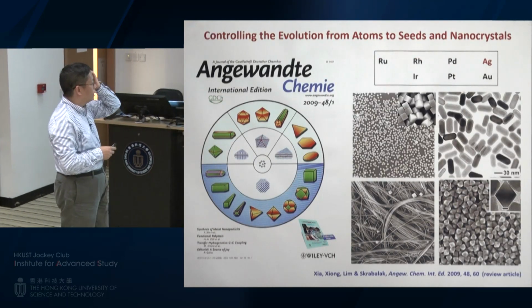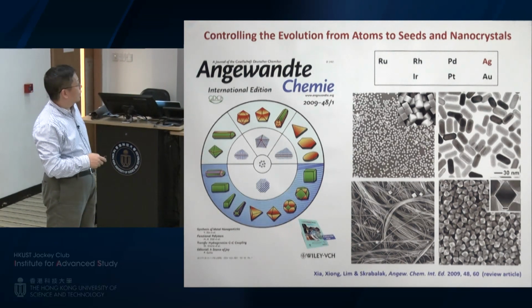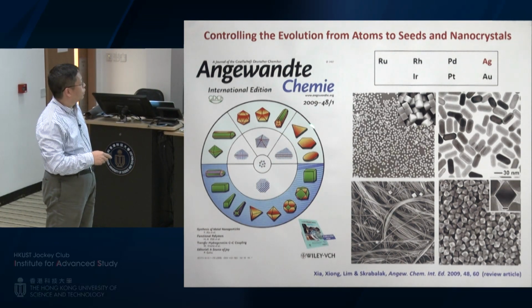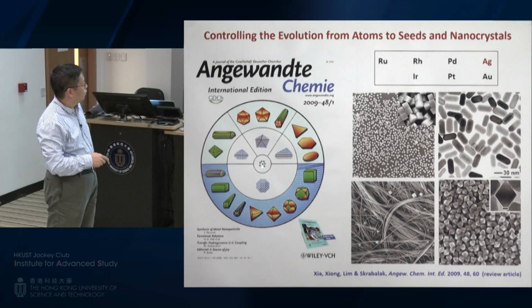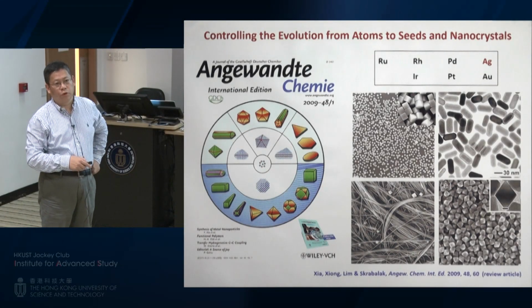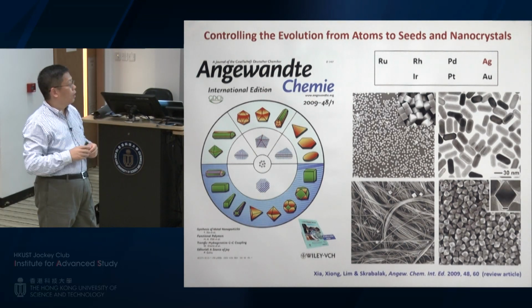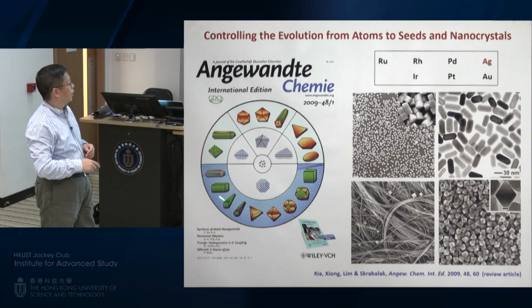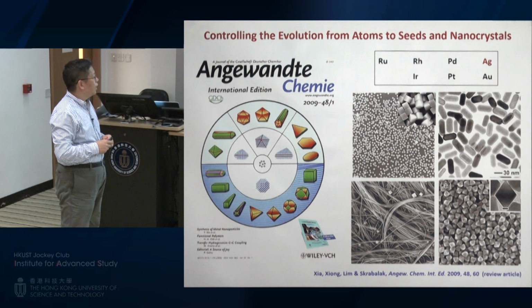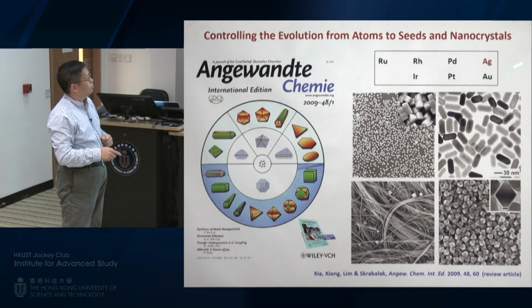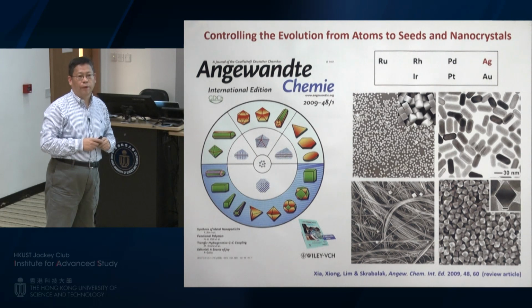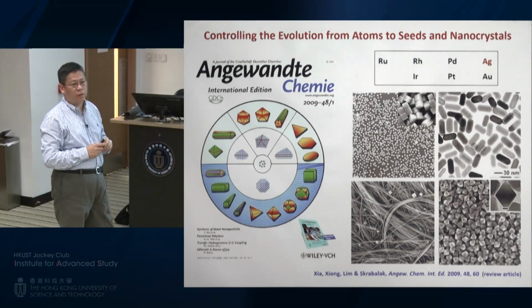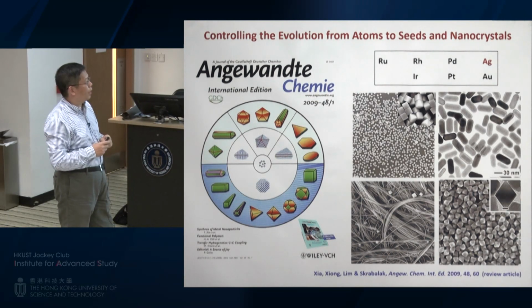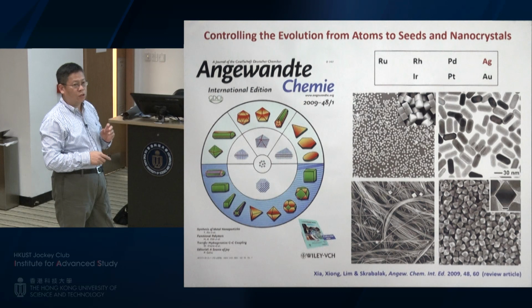And it turned out to be related to a number of things, as shown over here. Basically, when you think about formation of these nanocrystals or nanoparticles, they always go through like 2 major steps. First step is nucleation, and then you have growth. For nucleation, they're going to just form seeds, and seeds will be further enlarged, eventually making the final larger nanocrystals. And for metals, as shown over here, they are face-centered cubic metals. They have a tendency to form twin defects, because the energy needed, or energy penalty, for forming twin defects is so low for these systems. So that's why they always want to form twin defects.